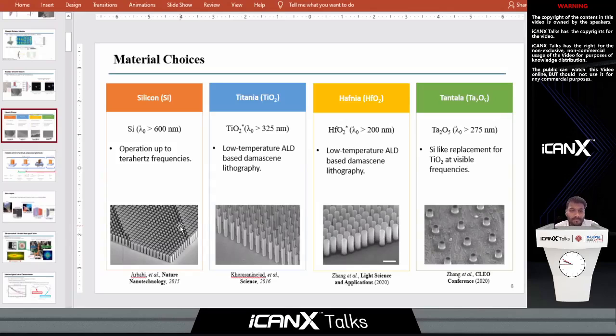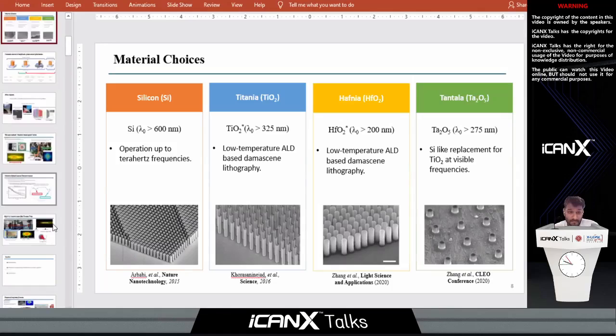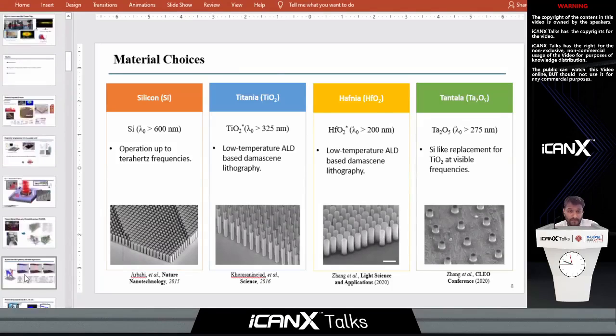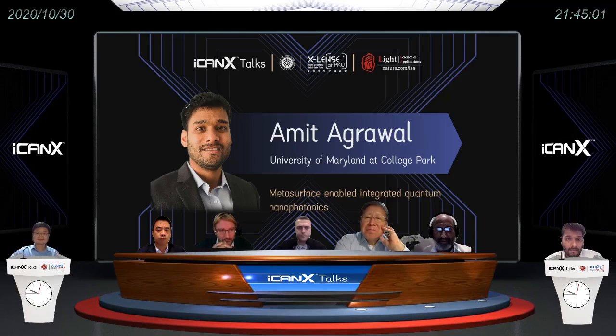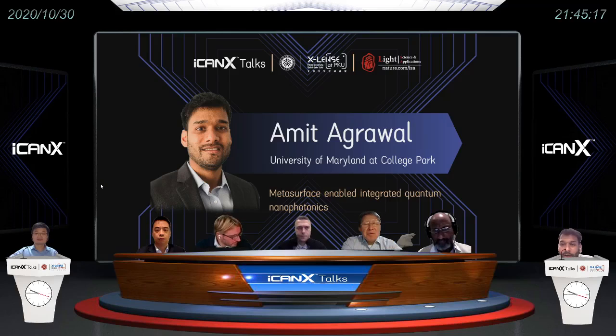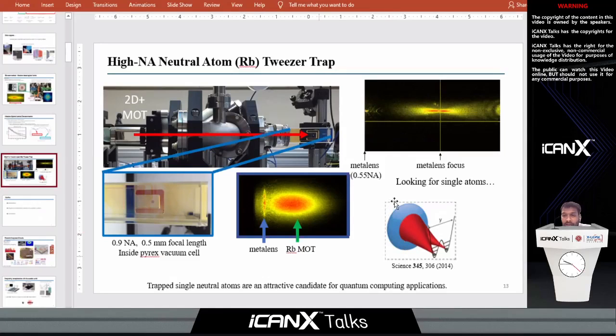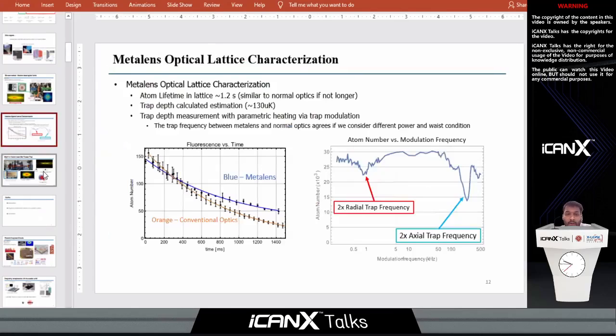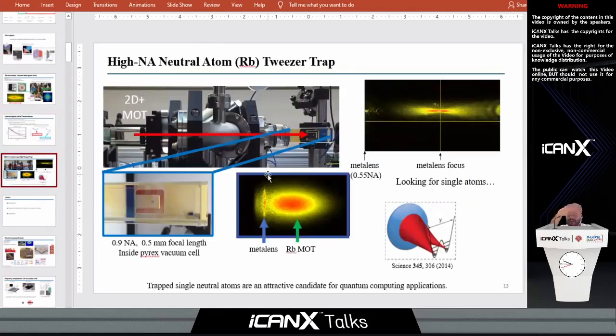Okay. Can I ask a question about your atom trapping? With all these meta surfaces, will you be able to create a two-dimensional array of atom traps? What are the challenges you think you'll face in terms of achieving that? So usually, currently, the approach is by using a lower numerical aperture lens with a very large field of view. And what they do is they modulate the beam using an acousto-optic modulator, both in X and Y direction, quite fast. And if you do it fast enough, then atom doesn't have time to leave the trap, right? So there's a lifetime to the atom shown here, let's say seconds, right? And I can modulate my AOM at megahertz speed, right? So you can basically deflect the light quite fast and then basically create an array of these traps where the atom doesn't have time to leave, right?